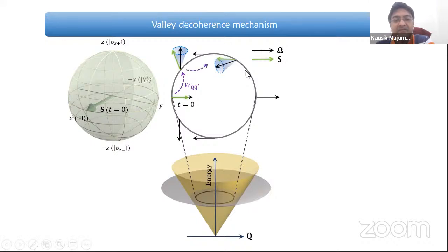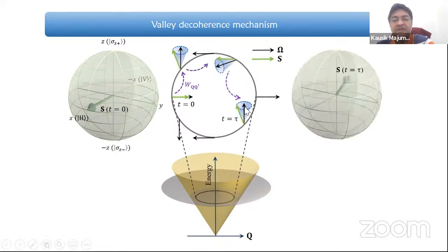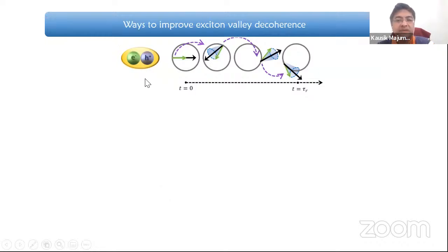It scatters and precesses, and keeps on happening until at some point the exciton recombines and radiates the light. At that point, whichever direction the pseudospin vector is pointing to, you measure the corresponding polarization in your experimental data. So your exciton is here, it scatters and precesses, and eventually along this direction you are measuring this thing.